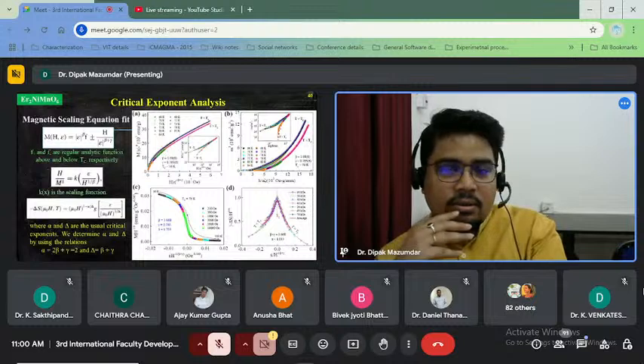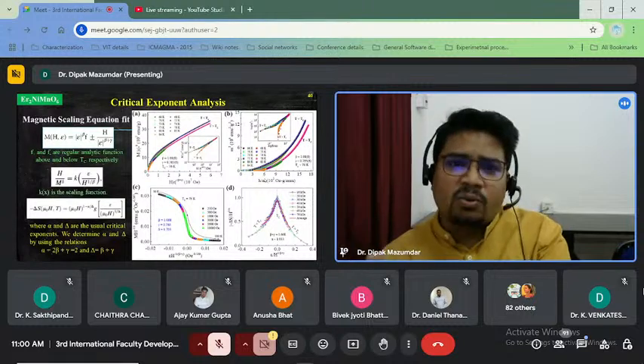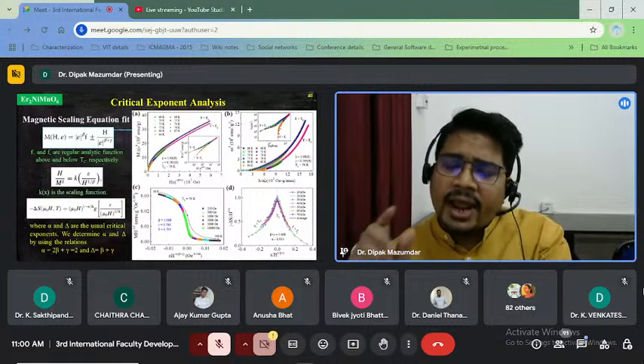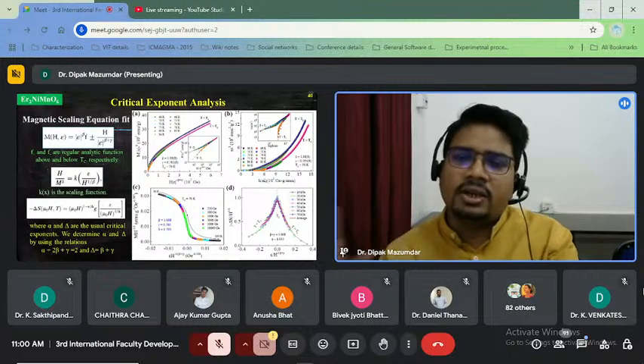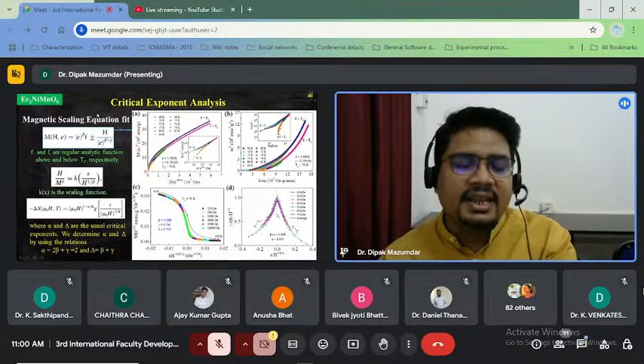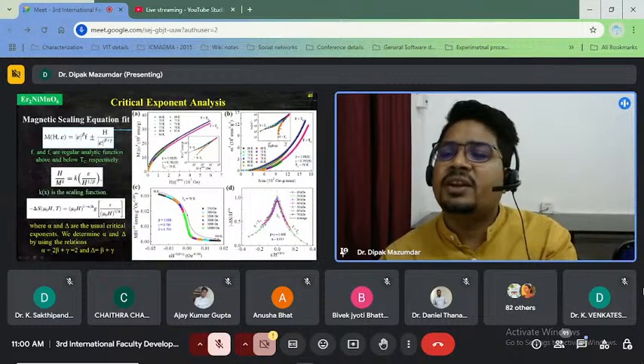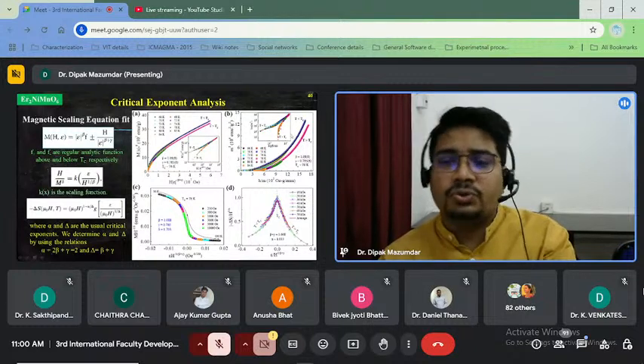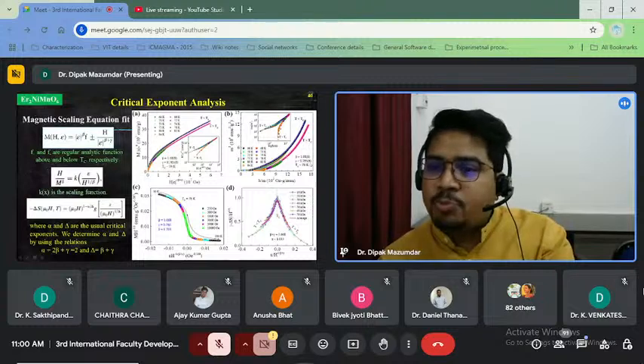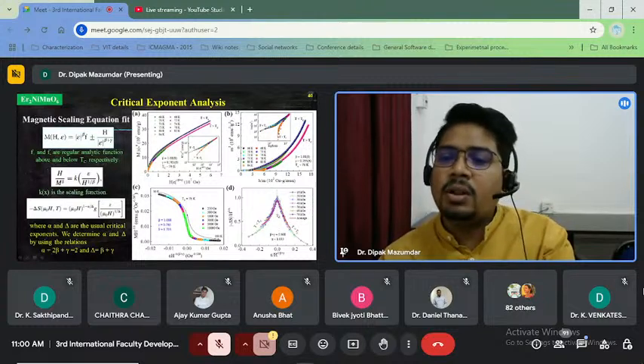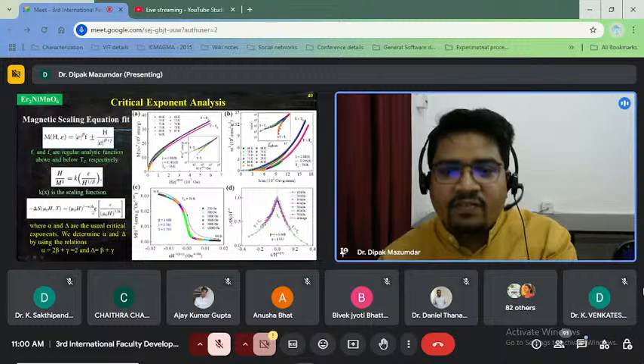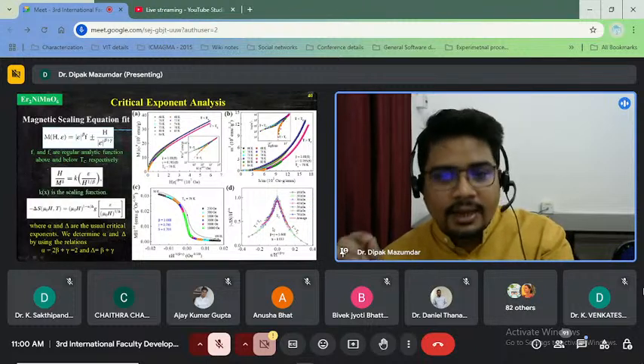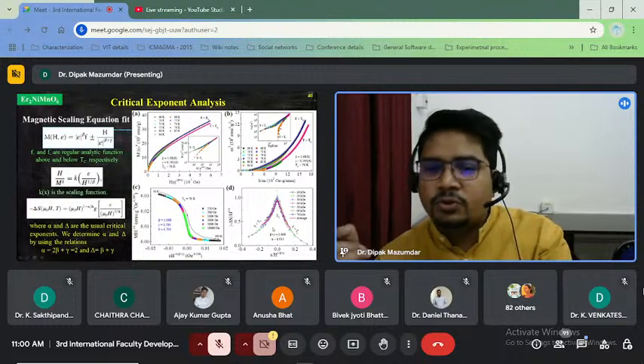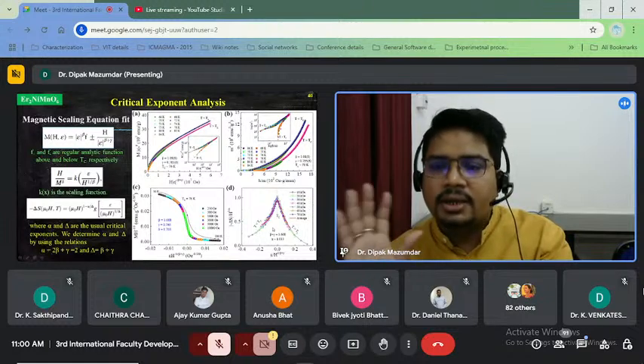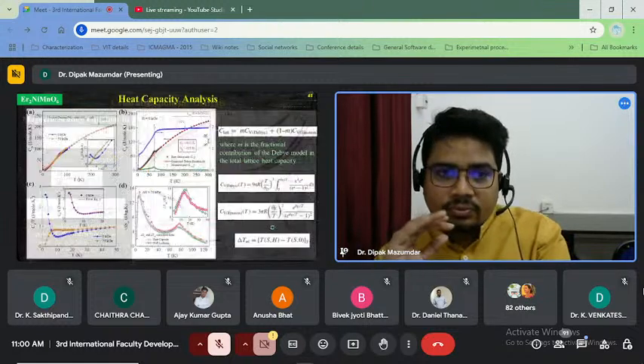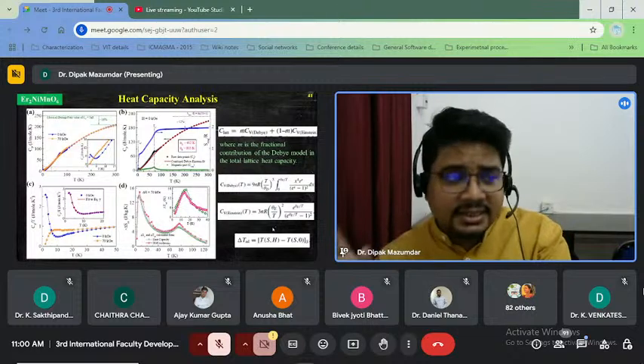So to check whether our experimental data or our analysis is correct or not, we have used this magnetic scaling equation, and it shows two different branches, and it also shows that our obtained exponents are correct. All the scaling functions also show that yes, the obtained values of beta, gamma, and delta are the same. So the possible explanations we'll discuss later.